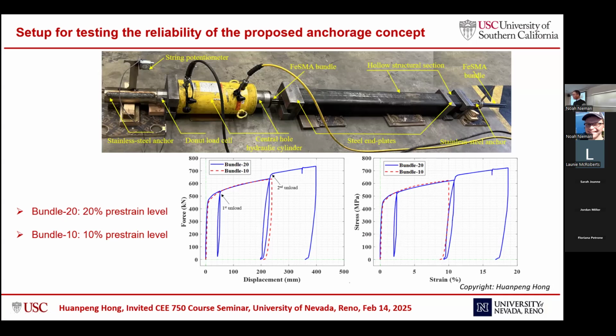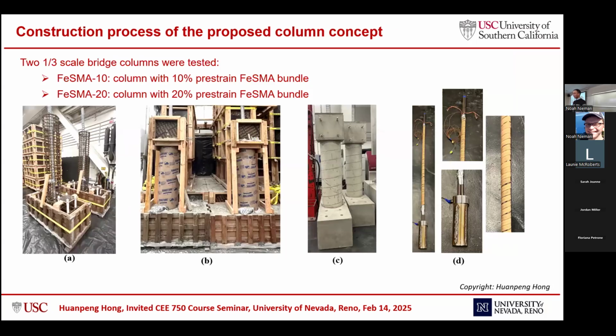So we are okay. We found this is reliable. And so after confirming all the feasibility of welding and also the anchoring, here we constructed 2 columns, 2 1/3 scale bridge columns. The first one, the iron SMA with the 10% pre-strain bundle, and the second one with a 20% pre-strain bundle. The construction process of this column is almost the same.